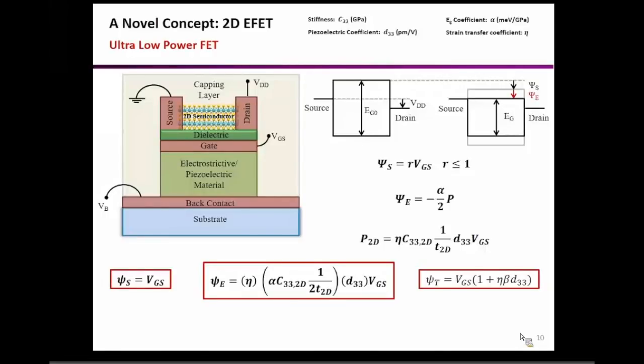Okay. Now my 2D material, its thickness is 1 or 2 nanometers. And you are compressing it by another nanometer. Even if I get 30% strain transfer, you will be contracting it by 30%. That's a huge amount of stress. That kind of correlates to this amount of pressure.